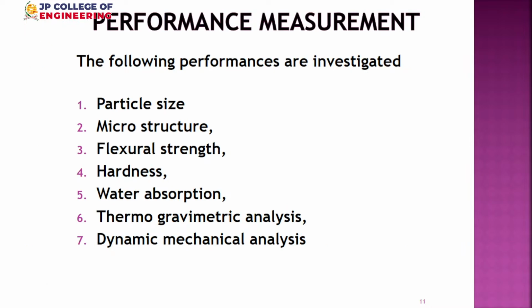Okay. So once the broad outline has been made, what are the tests we have done? That has been listed there. We measured the particle size based on the ball milling hours. We analyzed the microstructure, how our particles are distributed in the given matrix. We checked the flexural strength, hardness, and water absorption at low temperature and also at high temperature. And we went for thermogravimetric analysis. That is mainly the one, thermogravimetric analysis. It tells about the degradation of the polymer at elevated temperatures. So it heats your polymer and checks when it is going to degrade and how the degradation is going on. So all these items we can do.